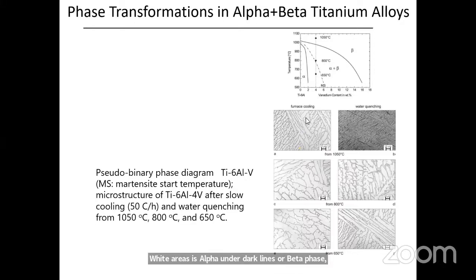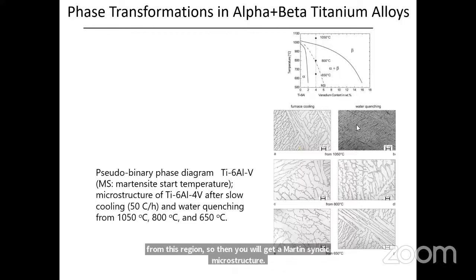Just similar to pearlite. If you heat the steel to the austenitic region, followed by slow cooling, you will get ferrite and pearlite, right? Similarly, here also you will get a lamellar kind of microstructure, that is alpha and beta. White areas are alpha and dark lines are beta. And rapid quenching leads to, if you are quenching from this region, then you will get a martensitic microstructure. So if you quench from this region, it is a kind of martensitic microstructure.